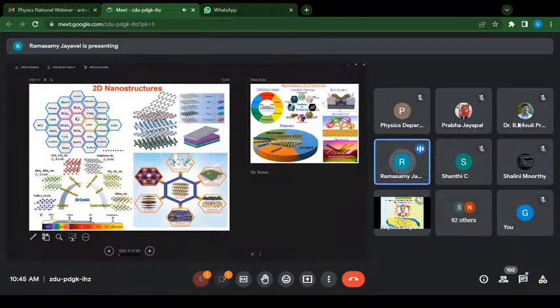And it is not a very easy job to just isolate this one. For example, if you have bulk, then the bulk has to be fragmented or separated in terms of its physical structure, without compromising the quality or, for example, the defects inside the structure. So the structural engineering is the major challenge here in terms of phase tuning or defect engineering. For example, if you have bulk material, defects like dislocations or imperfections have a very high influence on the functionalities and properties. But when it comes to this kind of single atomic layer thickness, even a small magnitude of defects will have a very large influence on the properties.